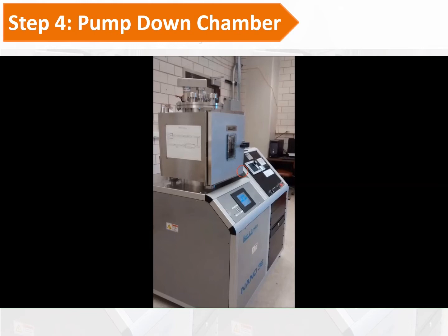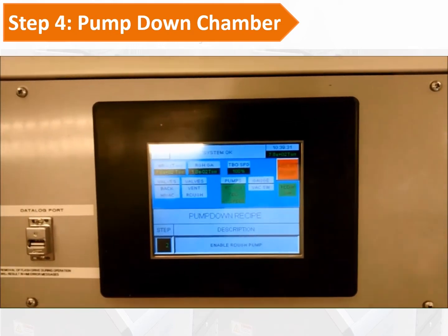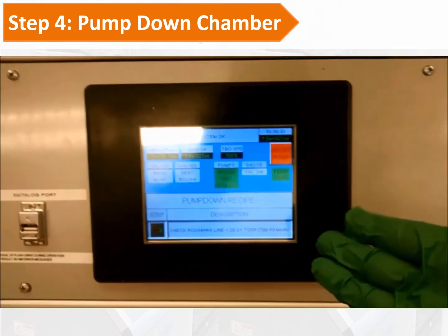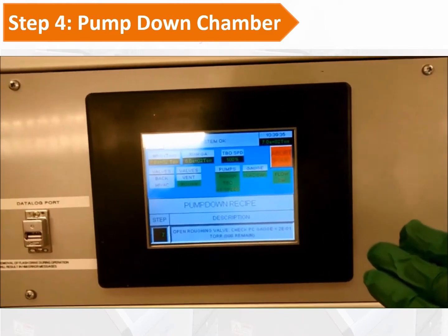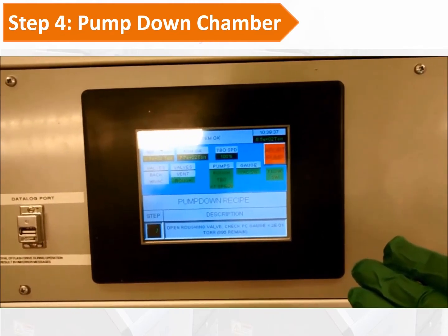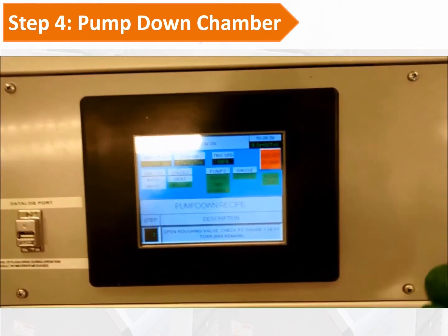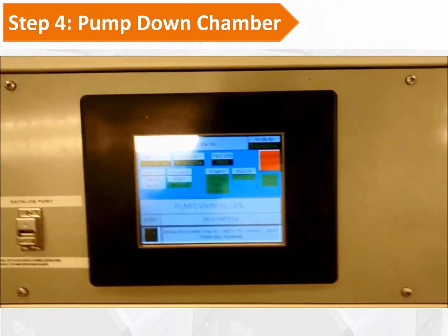If it does not drop in the next 15 minutes, it will abort the pump down process. Also wait until the pressure is less than 1 times 10 to the minus 5 torr, and you will find a green done button on the screen. It usually needs around 30 minutes for this process.